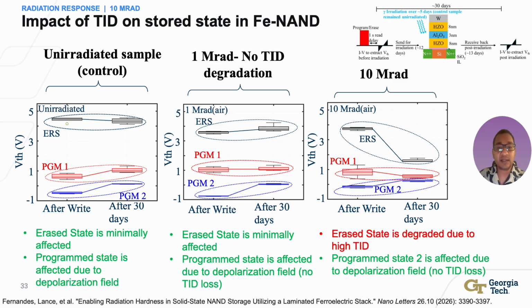The conclusion is that the useful polarization based states remain robust through 1 megarad and degrade only at a much more extreme accumulated dose. Even at 10 megarad, the device remains electrically functional. The observed shift identifies interfaces and trap charge as improvement targets, rather than showing catastrophic loss of ferroelectric switching.